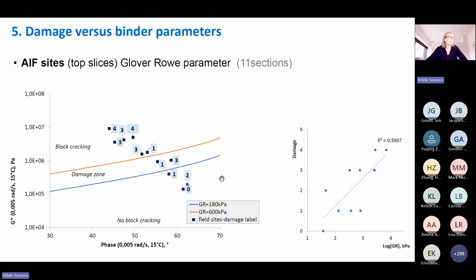So I looked a bit further at which ones these are, and you can see it's a highway and a highway, and this is a local road. So probably the traffic, as we expect, will play a role as well. And in this graph, you see the damage versus the logarithm of the Glover-Rowe. And the correlation is 0.59, which means, in fact, that the variation in the damage is for 59% determined by the logarithm of the Glover-Rowe, which is a lot if you consider all the variations between the sections.